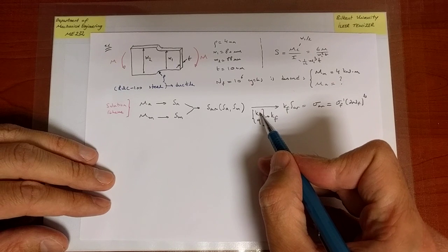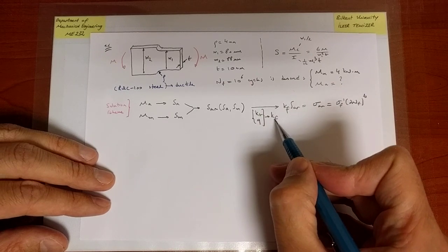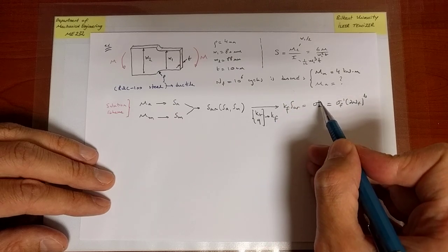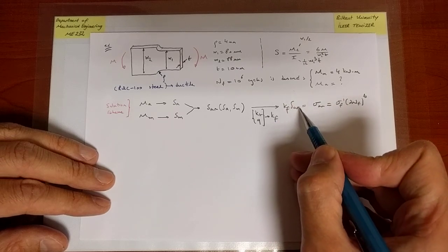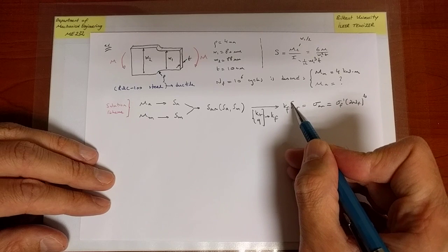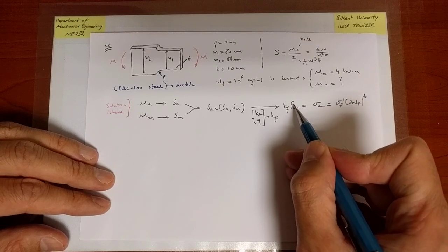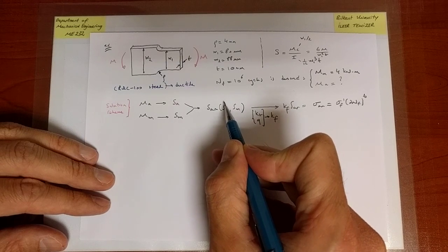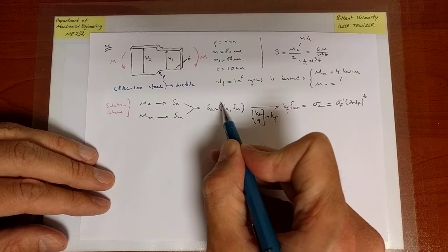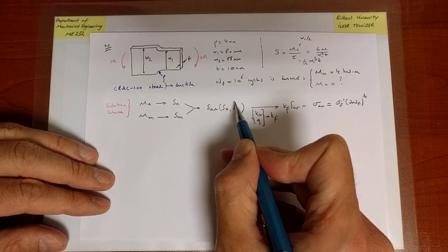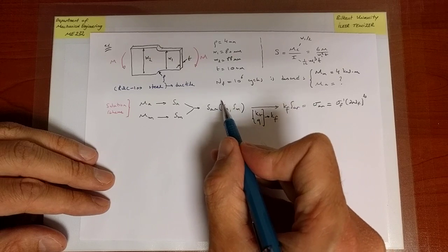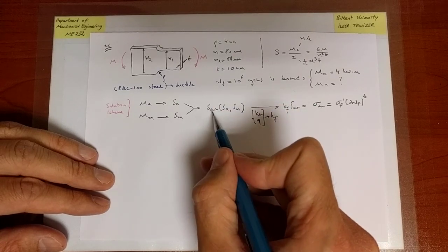From the geometry of the problem and by finding the value of Q, I can determine what KF is. Given this and KF, I can determine SAR, the equivalent completely reversed nominal stress amplitude. So I know SAR, and it's a given function of SA and SM. In the present case, remember that we're going to prefer using either modified Goodman or the SWT equation. But I know this equation.